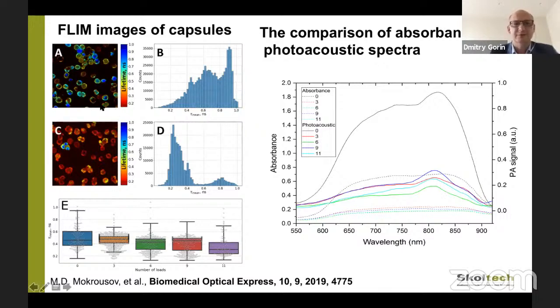We use FLIM, fluorescence lifetime imaging. Here you can see the fluorescence lifetime of indocyanine green only in the shell. And this is after 11 cycles of the freezing-induced loading method inside of the shell. We obtain a decrease in the fluorescence lifetime, which confirms that we have real fluorescence quenching. And here you can see absorption and photoacoustic spectra. We again have broad absorption in the window of transparency of biological tissue, between 600 and 800 nanometers.